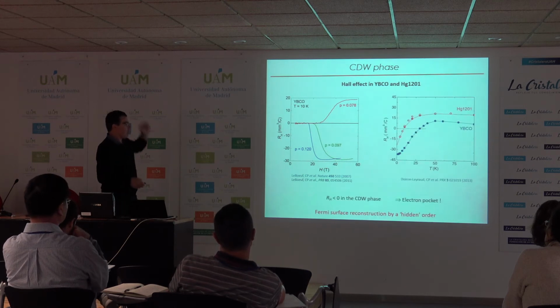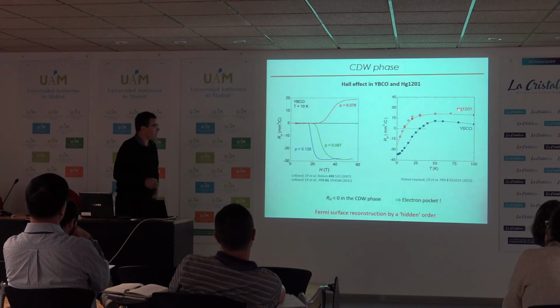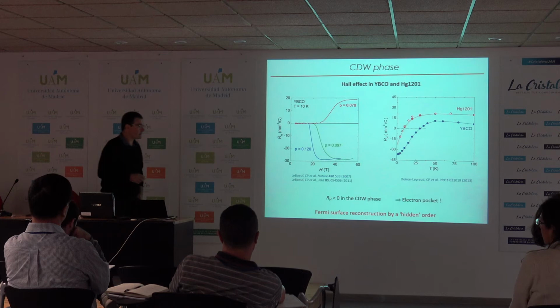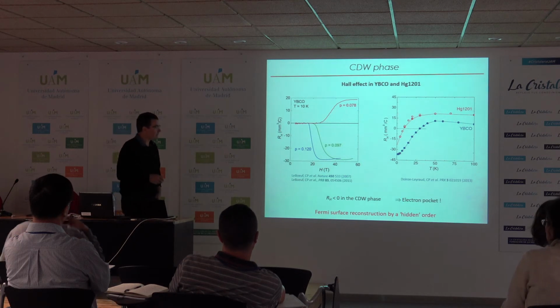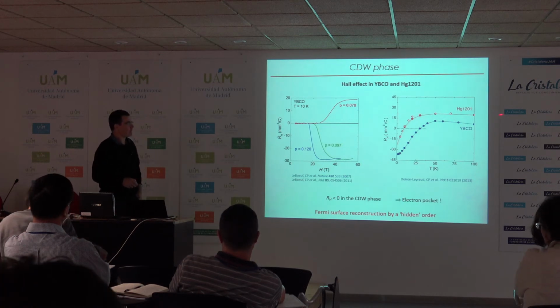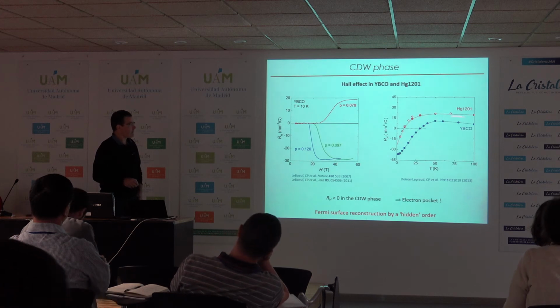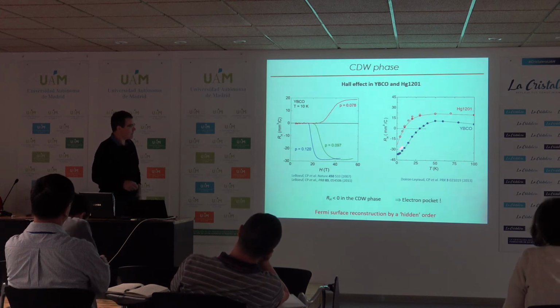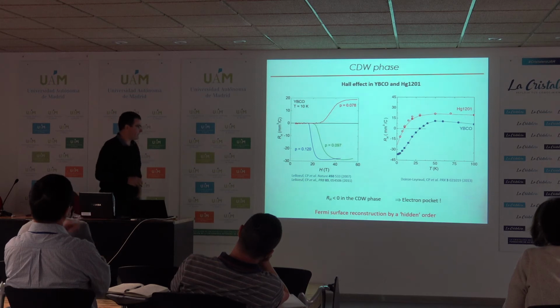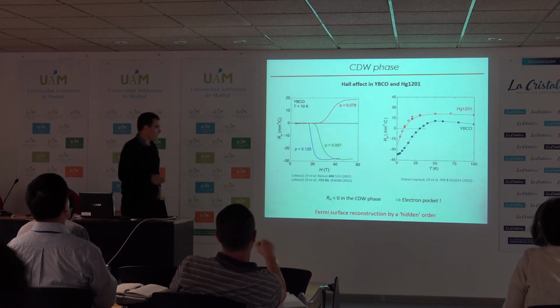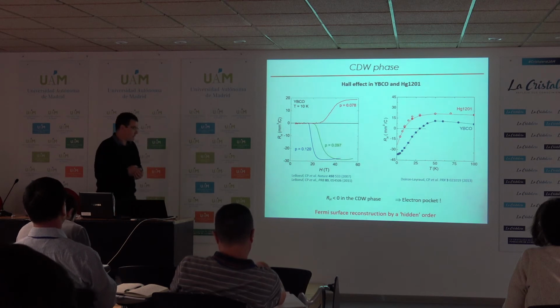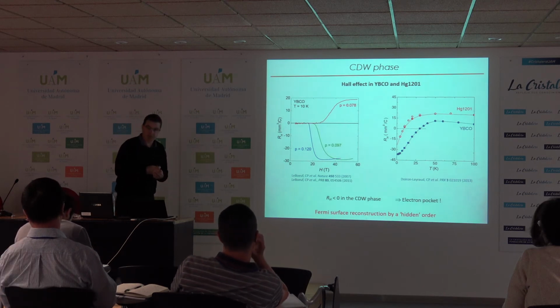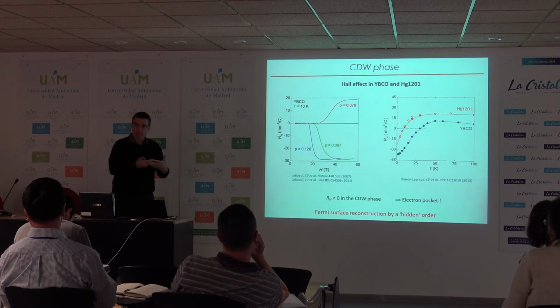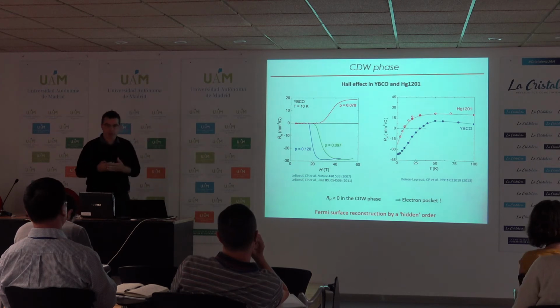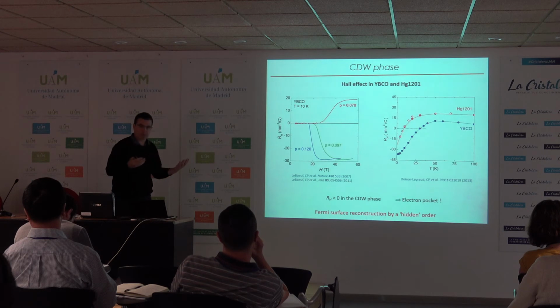So here I show Hall coefficient versus temperature, now for two compounds, not only YBCO, but also the mercury 1201. So there is the same phenomenology. Basically the Hall coefficient is positive at high temperature, but below a certain temperature you see that it becomes strongly negative. And a negative Hall coefficient means that you have an electron pocket in the Fermi surface. An electron pocket in the Fermi surface of an underdoped cuprate means that somewhere you have a Fermi surface reconstruction.